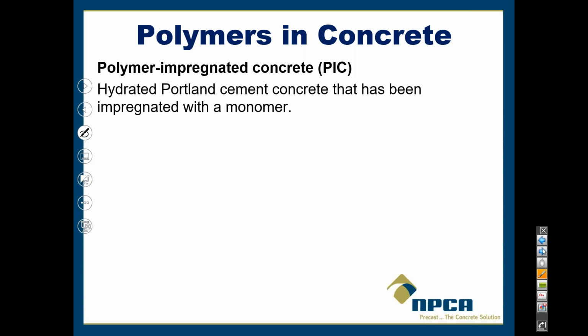So how this works, and this is quite an involved process, but it could be done. It's actually very applicable more to precast, I think, than it would be to cast in place. So there's a few stages with it. First of all, you have a piece of concrete and you want to impregnate it with polymers. You can do it partially, which is usually 85% or less of the voids filled with this polymer, or you can do a full impregnation. A partial impregnation would be less than that. And that's where maybe you would just impregnate the very top surface of a concrete, because that's what's going to be exposed to a very harsh environment, right?